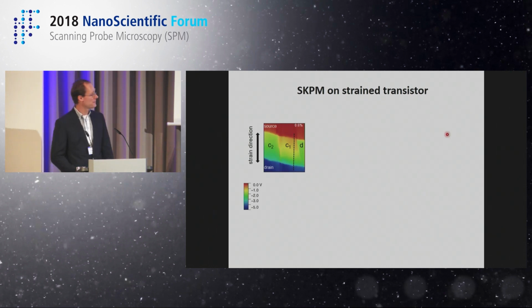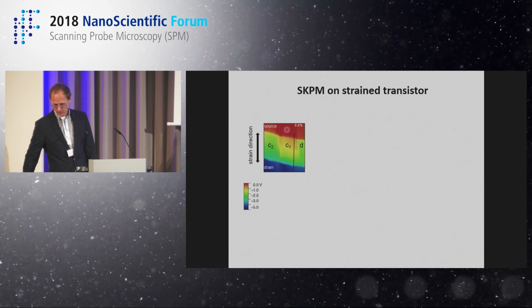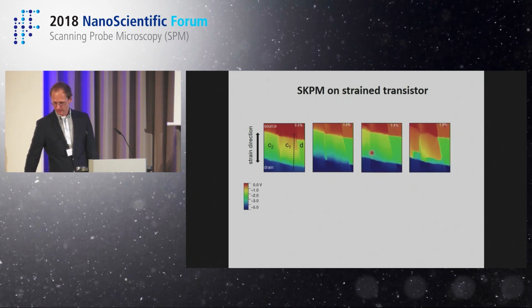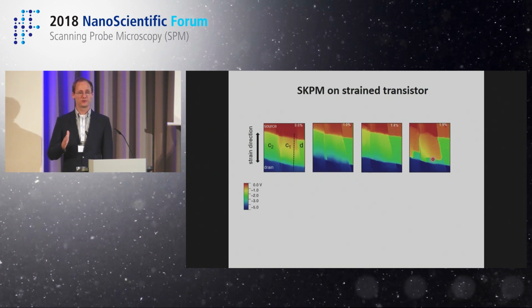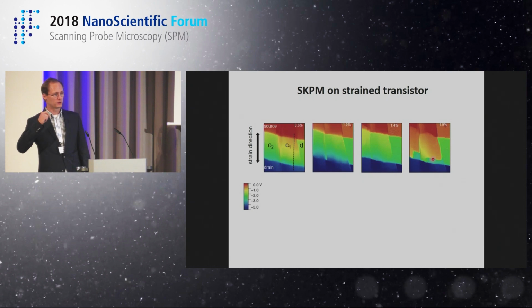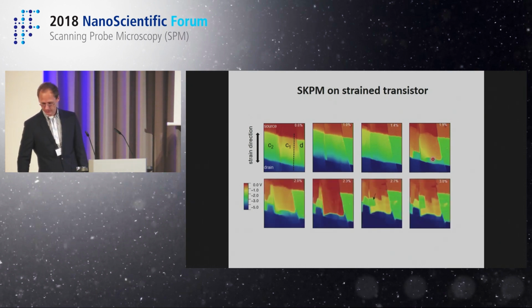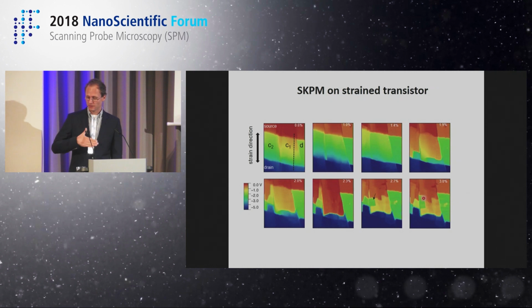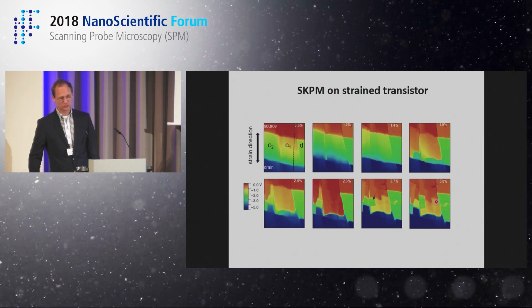If I instead look at the KPFM map, things get interesting. Initially, I see the voltages between source and drain, the crystals that bridge the two electrodes, and now I apply 1% strain. I see that the electric field starts to increase at the contacts, which means that charge injection gets more difficult at these contacts. I start to apply more and more strain, and I see the appearance of abrupt changes in surface potential, which always means that locally I have a very strong electric field, and this electric field is needed in order to push carriers over a barrier that emerges. And at the end, if I go to the completely destroyed device, I see that I have a lot of these local barriers where a strong electric field is needed in order to overcome transport.